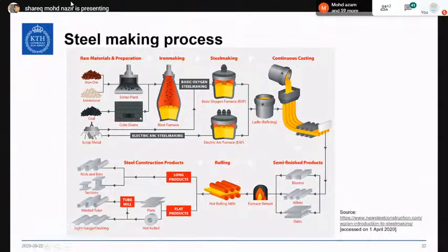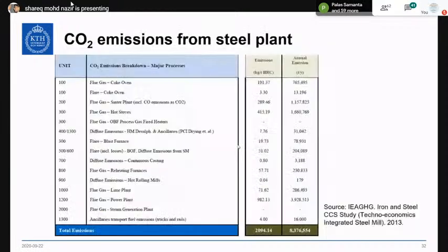Now we see that we are basically using coal in the process here to reduce the iron ore. Now what happens here is we see the emissions we discussed before, nearly 2 ton CO2, just 2000 kgs CO2 per ton of steel that is being produced. It's a very similar number here. And the majority of the emissions comes from the flue gas from the coke ovens. It comes from the sintering plant. Then it comes from the hot stoves, which is nothing but the blast furnace and the basic oxygen furnace. We have majority of the emissions, close to 25% of it, and then we have the power plant of the steel plant that is emitting nearly half of the CO2 that is emitted from the steel plant.